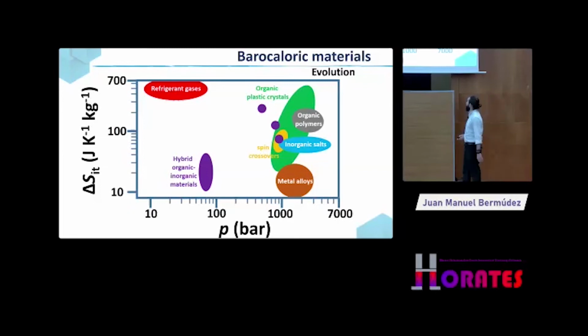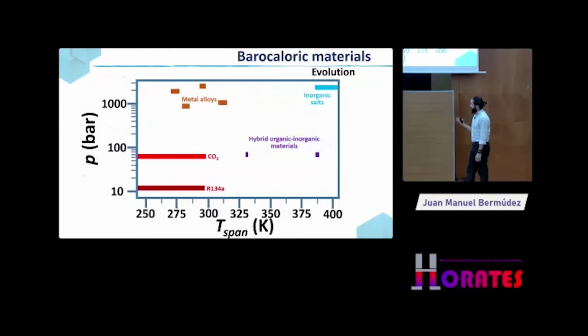So we are reaching the point of being competitive with the refrigerant gases. The field is reaching that point, but there is still a limitation, which is decreasing the pressure that you require to drive this phase transition. In terms of the temperature span, those materials have been evolving over time. We managed to improve the temperature span of the barocaloric hybrid materials, closer to room temperature and larger than before, but at the expense of using more pressure.